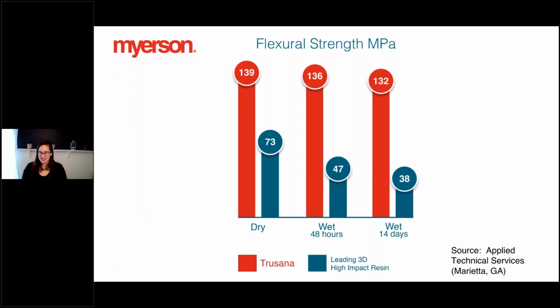Again, we did the same test, exposing the resin printed parts to water for 14 continuous days. And again, the flexural strength remains, compared to the other material where it steadily decreases. And these results as well were performed by the same unbiased third party. So we're really aiming to show on the spec sheet, you get the properties that are advertised with Trusana.